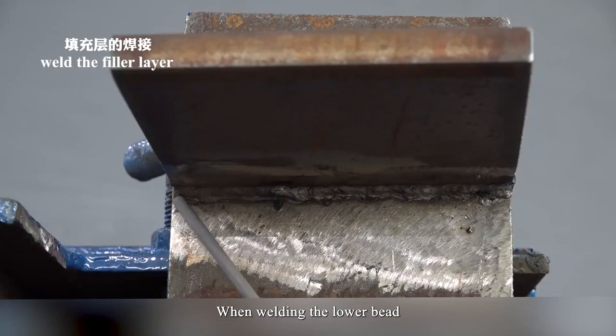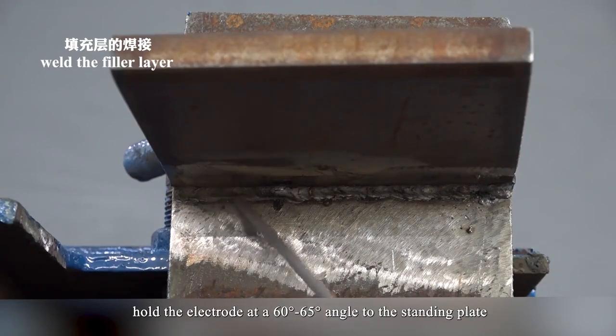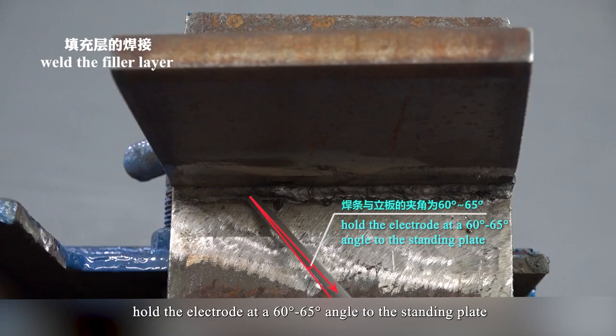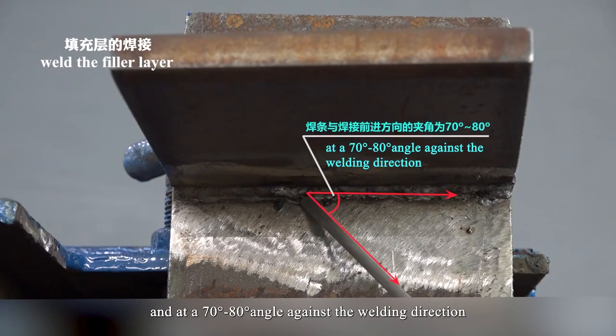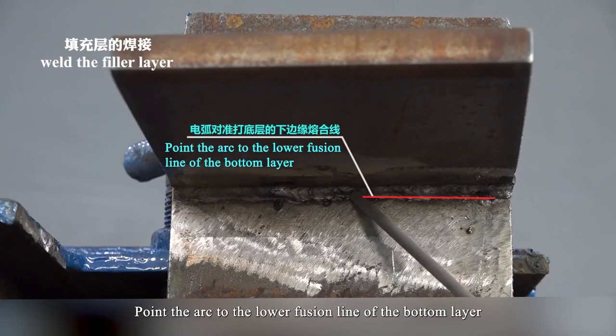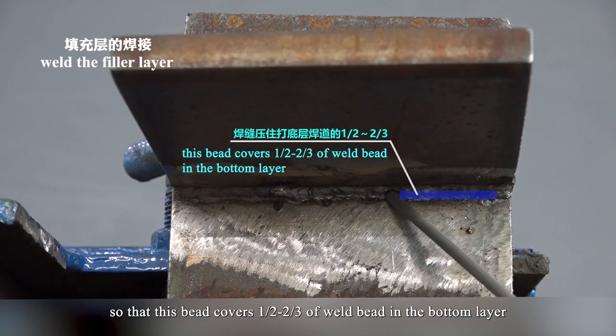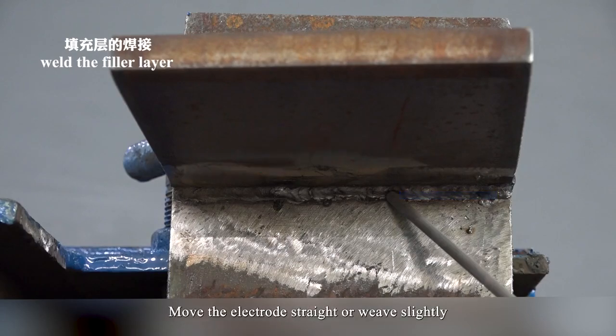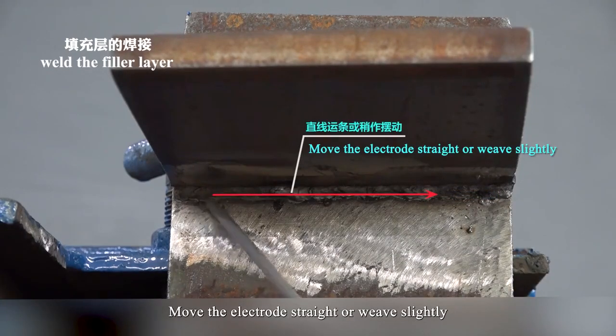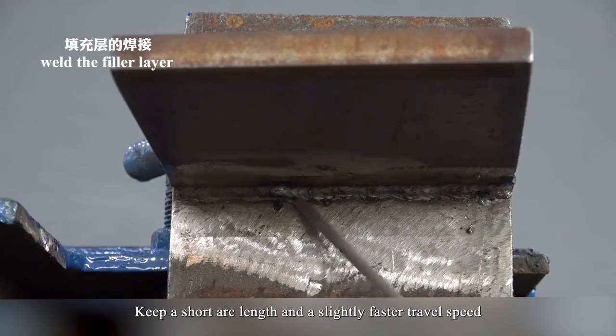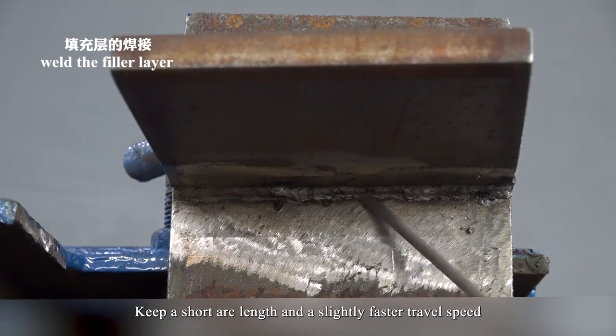When welding the lower bead, hold the electrode at a 60 to 65-degree angle to the standing plate and at a 70 to 80-degree angle against the welding direction. Point the arc to the lower fusion line of the bottom layer so that this bead covers 1/2 to 2/3 of weld bead in the bottom layer. Move the electrode straight or weave slightly. Keep a short arc length and slightly faster travel speed.